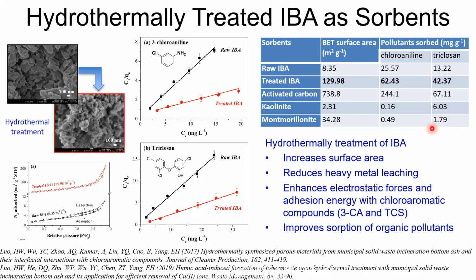The first trial approach is using hydrothermal treatment to treat IBA, because by doing that we are able to increase the surface area and stabilize the heavy metal. The BET results show that after treatment, the absorption capacity is much increased, and the surface area of the treated IBA is much improved compared with the raw IBA.